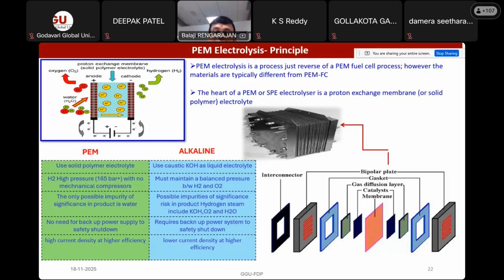And the second advantage is that it's a very thin separator as well as the membrane. Because of that, you can coat the electrocatalyst, that is the positive and negative electrode material, on the membrane itself. So you can considerably reduce the inter-electrode distance, because the inter-electrode distance is nothing but the membrane thickness. If you have a micron-level membrane, 150 micron, 175 micron, or 100 micron, that is the distance between these two electrodes, only the 100 micron. So you can considerably reduce the inter-electrode distance, and you can increase the ionic conduction without adding any salt,